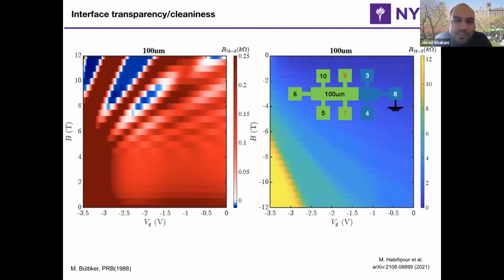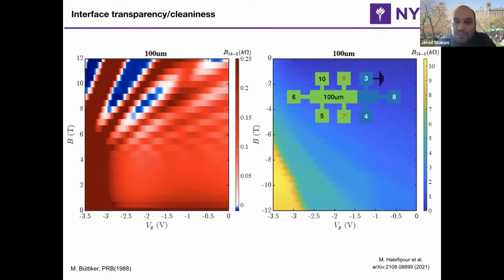So in the dirty sample that I just showed you data from, this is the third dirty sample. You see the data on the left is very similar. There is a negative resistance, but it's small. But on the right side, basically we ground the superconductor on pin number 8 in this particular setup. And in the next slide, I'm going to ground the superconductor on pin number 3. So I don't know if you notice any difference.